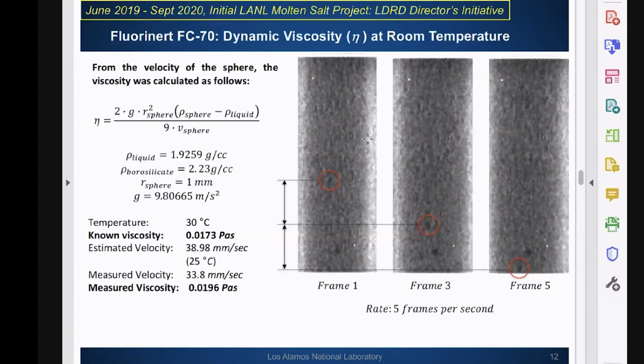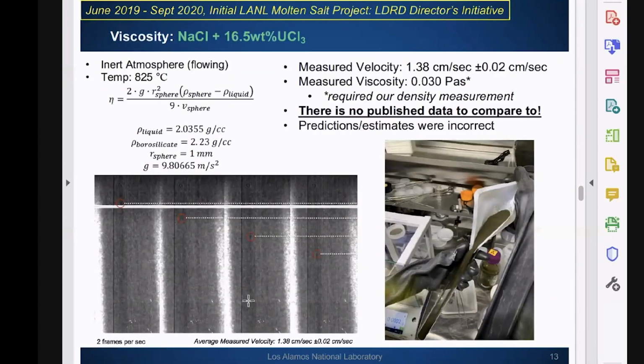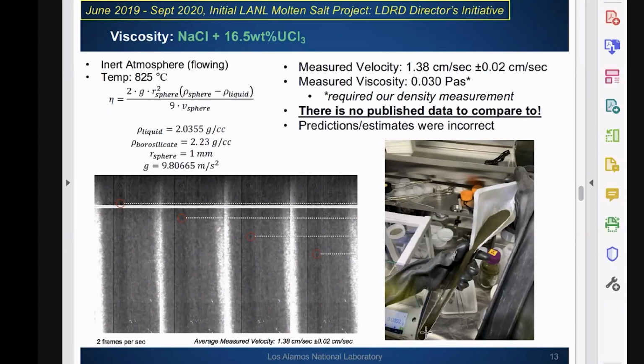So here's just some quick examples of the results. So we first started off again with our calibrating fluid. We found a relatively close match to the known viscosity and moved on to our molten salt sample from there. With this, we used uranium-bearing sodium chloride, and that's me loading the quartz tube for this experiment on the right here. And what I wanted to point out here is that what ended up happening is it was much faster through the molten salt than we expected. And so this was interesting.